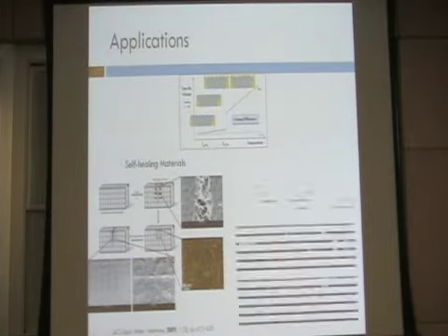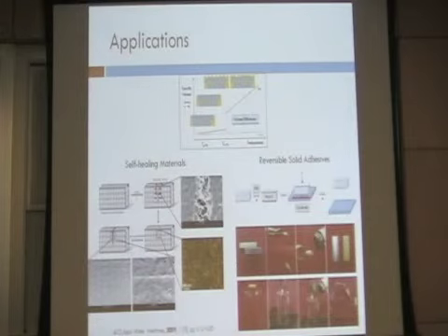Also, we know that the thermoplastic component, PCL, is a very good hot melt adhesive. Once the material is heated, all the surfaces are covered with a thin layer of PCL, so we can use this material as an adhesive. It's a very unique adhesive because it has a high degree of structural rigidity in the adhesive state. And the adhesion comes from the crystallization of PCL, so we can easily go above its melting temperature to break the adhesive bond. That renders reversible adhesion to our material.